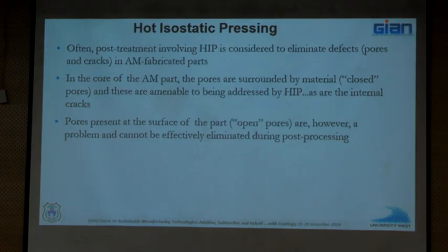No, it's simply because if it's open, then the application of pressure has no impact on the microstructure because it's open, right? On the other hand, if it is closed, then application of pressure and temperature can heal that defect. Correct, right?